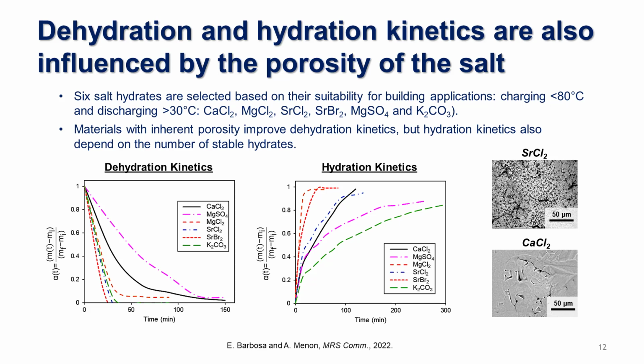So we can dehydrate them. Here's a normalized extent of dehydration, where 1 is the fully hydrated salt and 0 is the fully dehydrated, or anhydrous, salt. You can see that out of the different salts, some of them tend to dehydrate very quickly, while some of these other ones like magnesium sulfate are very sluggish. It takes a long time for the magnesium sulfate to dehydrate. And this is just 100 milligrams of material. If you're working with grams and kilograms, these time scales can be even over several days, and so that's very undesirable.